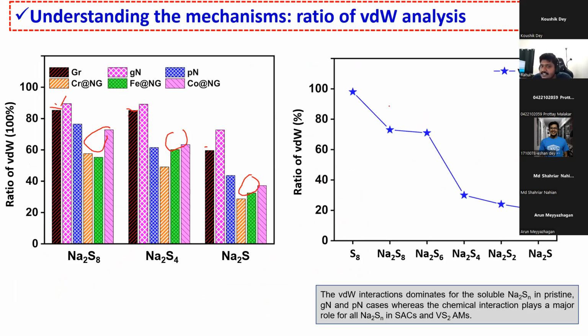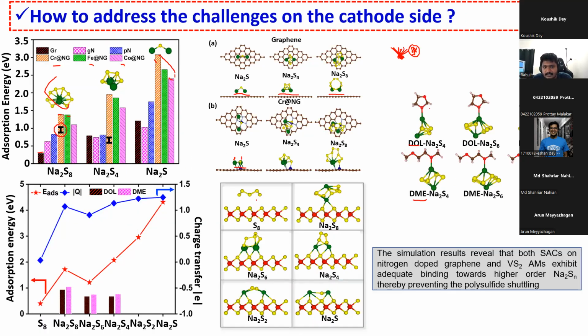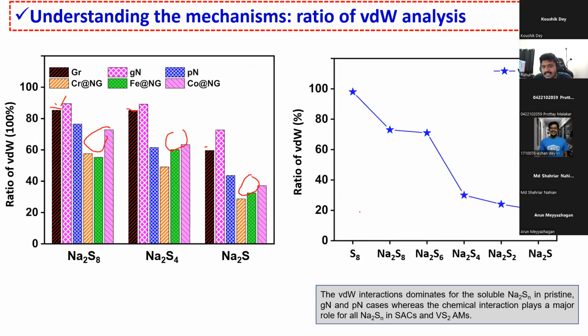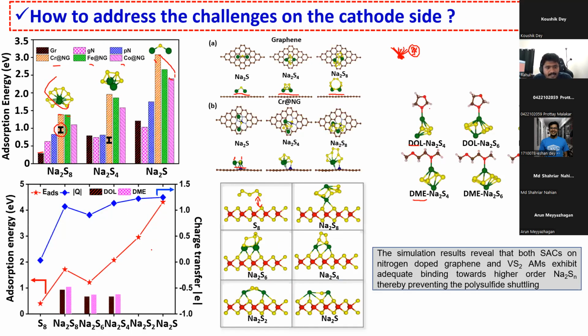And for the VS2 substrate also, for the S8, you can see that there is no chemical interaction between them, only the weak physical interaction. That's the reason why you are seeing the maximum ratio of van der Waals interaction from that. But when we move down the line from S8 to Na2S, you can see that Na2S has the lowest van der Waals interaction. That means it has the highest chemical interaction. That's the reason why Na2S has higher binding energy when compared to the other systems.